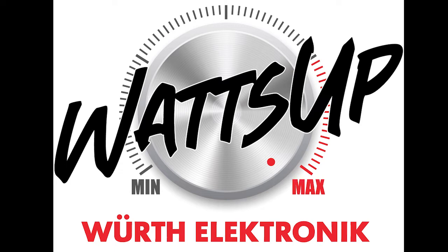This leads to our first design tip: find suitable core materials. For switching frequencies under 100 kilohertz, you should use iron powder, ferrite, superflux. And from Würth Elektronik, the PERM series is suitable. For a switching frequency between 100 and 1000 kilohertz, you could use ferrite, superflux, and again, the PERM series. And finally, for a switching frequency of greater than 1000 kilohertz, it's best to use ferrite. The PERM is suitable for all three types of switching frequencies.